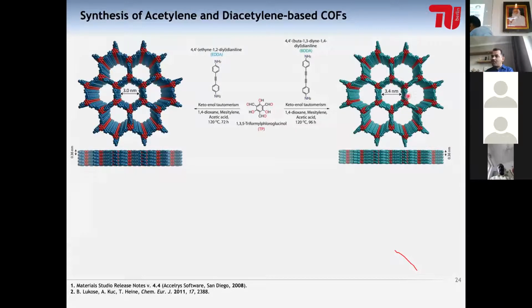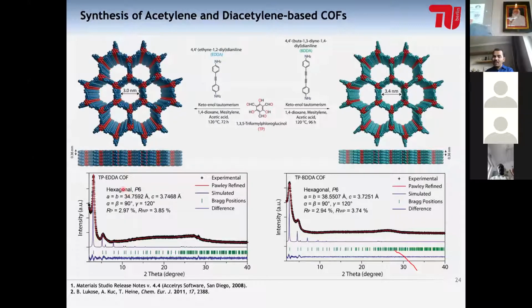And it should have a pore size of 3.4 nanometer. The other acetylene-based material should have the pore size of 3 nanometer. And these materials should have a crystallinity as well. And for the first time, what we did was we did the powder X-ray diffraction analysis. And here we can see that now these materials have definite peaks, which show that these are the crystalline materials.